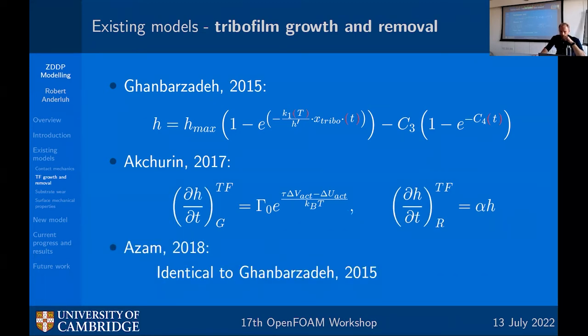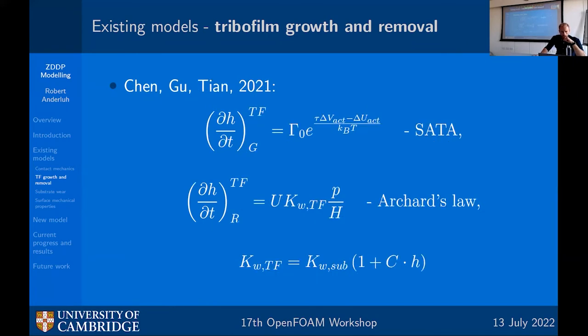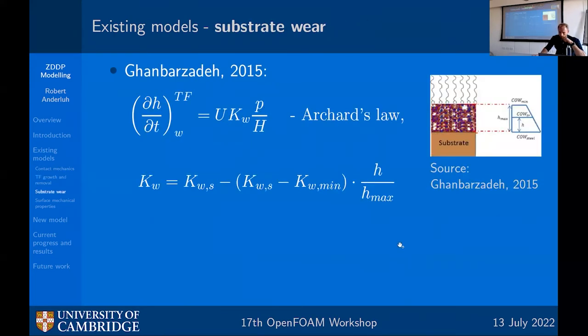And Azam in 2018 used the same model as Ghanbarzadeh in 2015. And in 2021, we had Chen, Gu, Tian, who used also the SATA model for growth. And then interestingly, for removal of the tribofilm, they use Archard's law. So same as presented by Luca, where we have the sliding velocity and dimensionless wear coefficient, contact pressure, and hardness of the surface. And they modeled the wear coefficient as linearly dependent on the local tribofilm thickness.